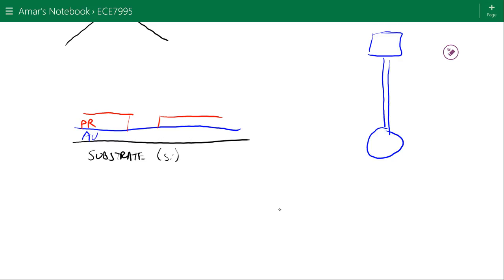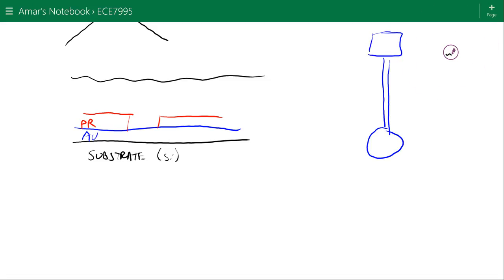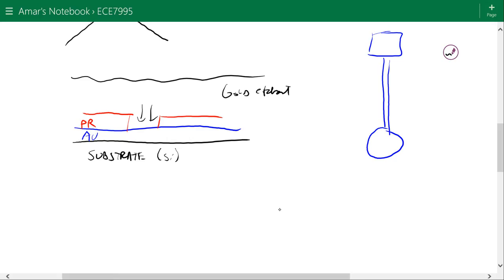The next step is to transfer the pattern on the photoresist to the gold layer underneath it. We can take this whole thing and dip it into a gold etchant. When we dip it in that bath, the gold etchant will start etching away the gold, and we time the etching so that we remove just the unprotected section of gold. We end up with just the gold layer remaining under the photoresist.